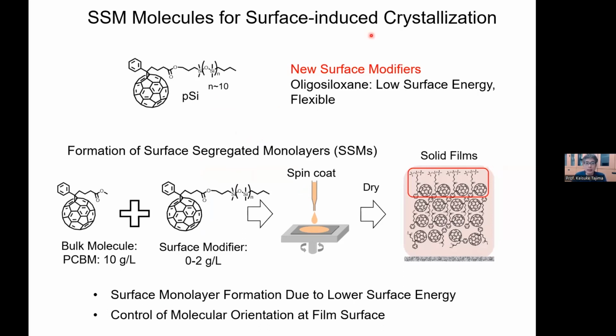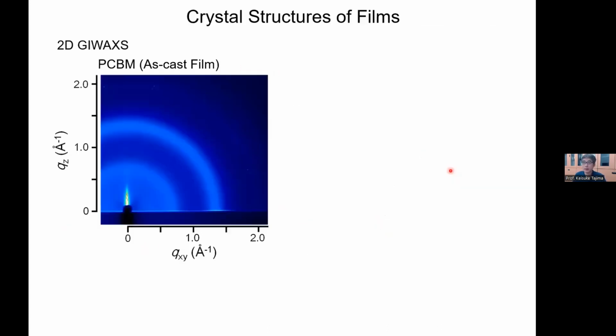So what we did is similar to the original molecular design, but with fluorine replaced by oligosiloxane. This oligosiloxane also has a low surface energy comparable to the fluorine chain, and it's a lot more flexible than the fluorine chain. We did the same mixing and spin coating experiment as for the fluorine derivative to get the thin film. And it works. I won't go into the detail, but the silicon version also works as a surface segregated monolayer on top of the film.